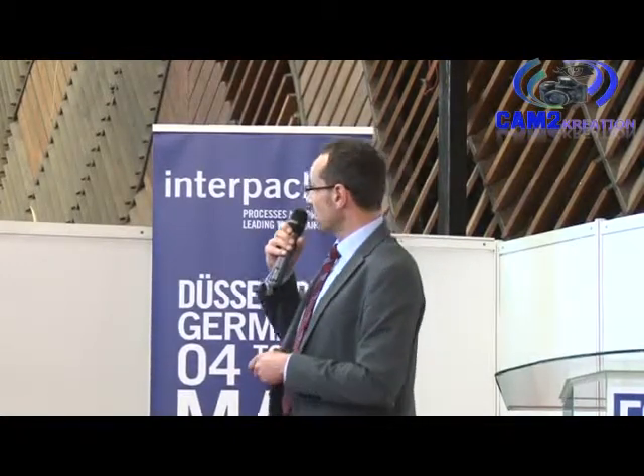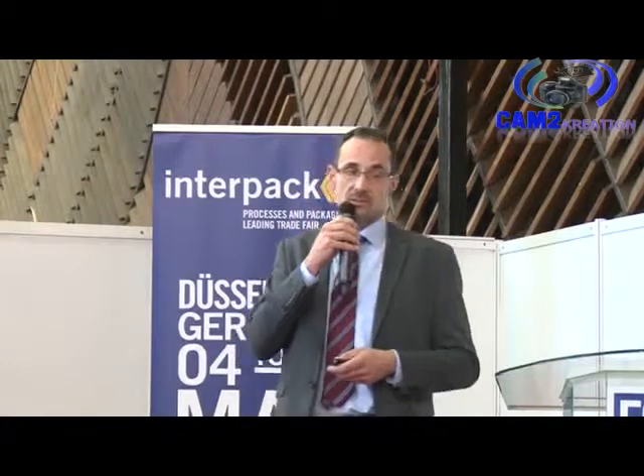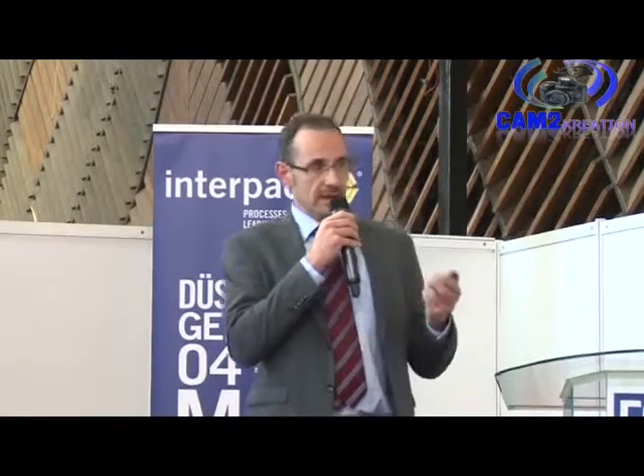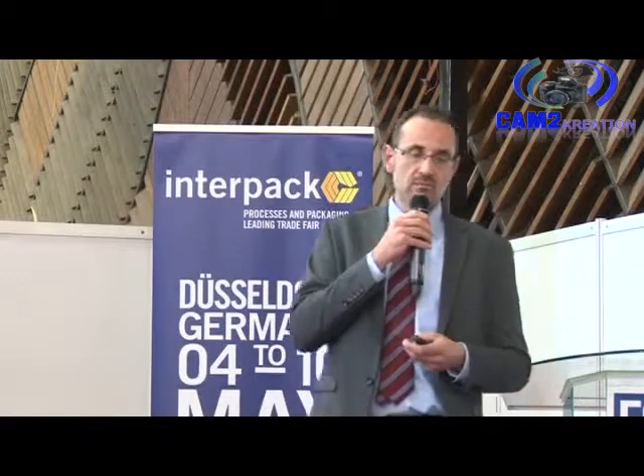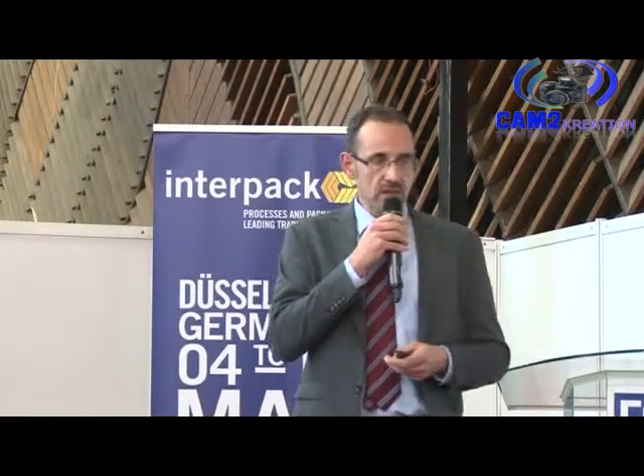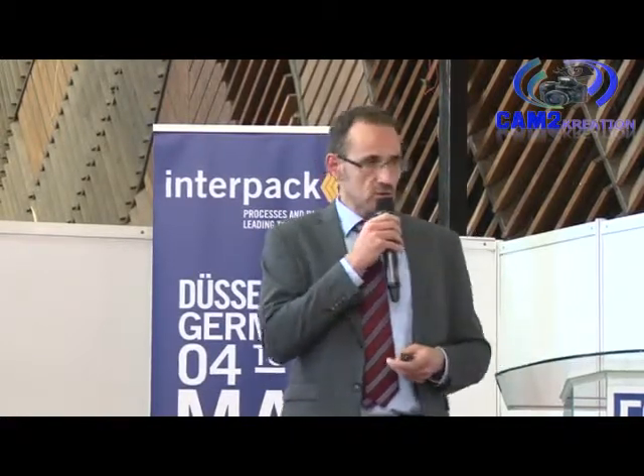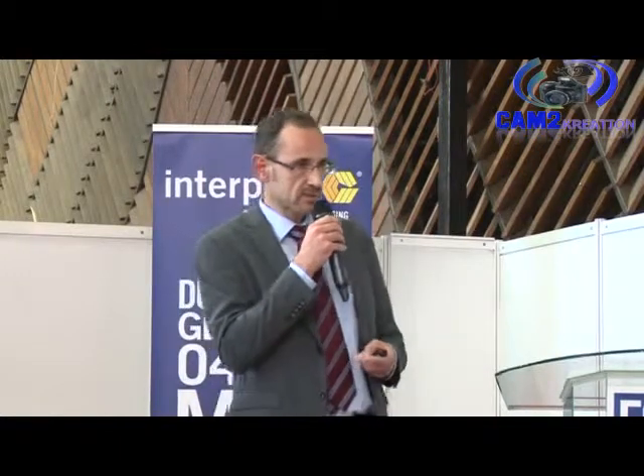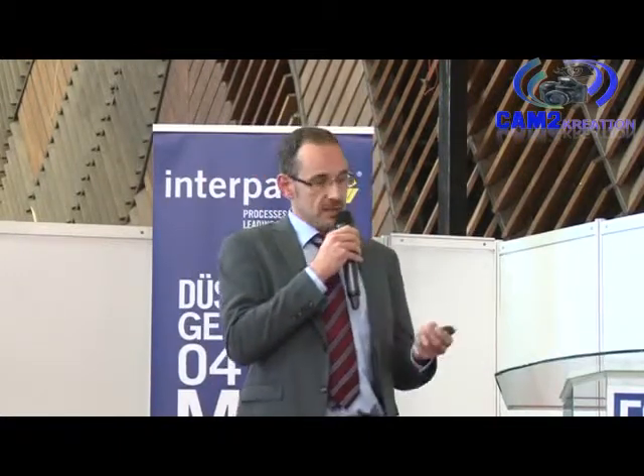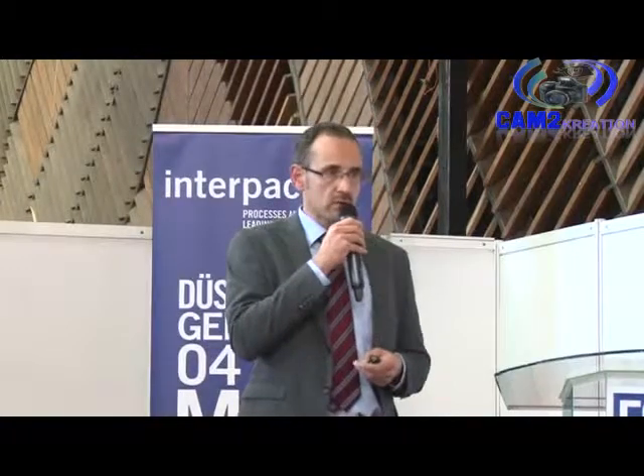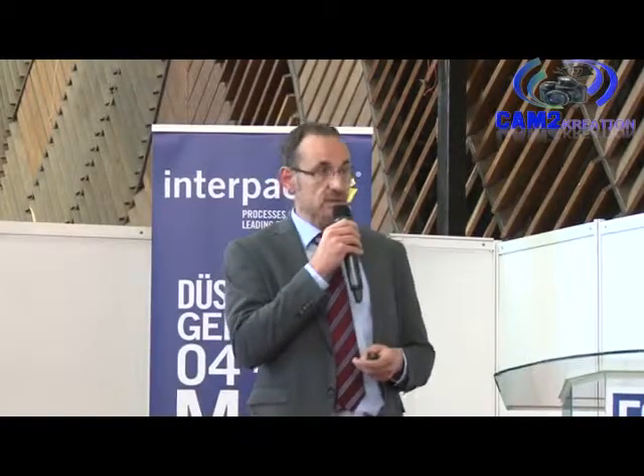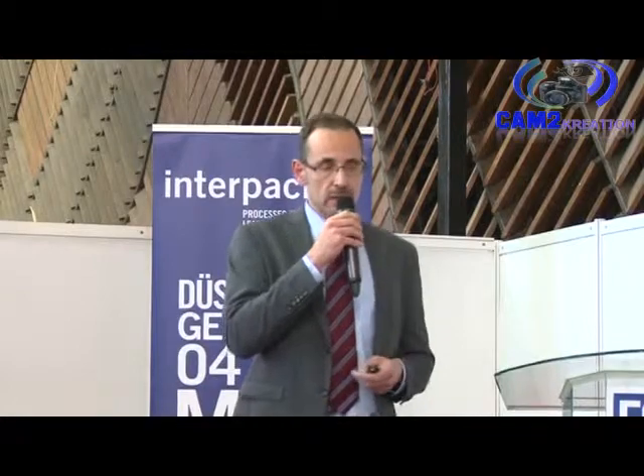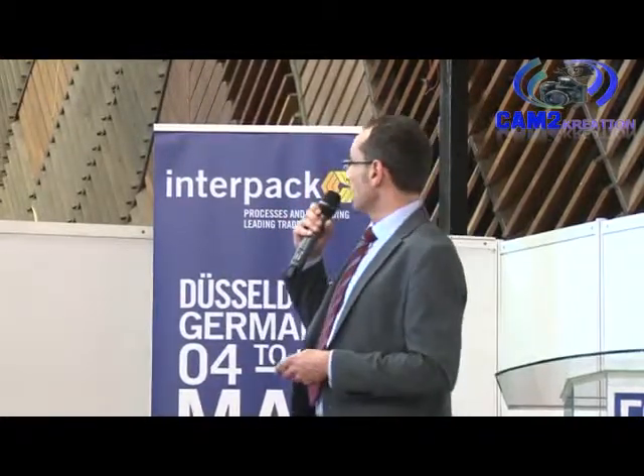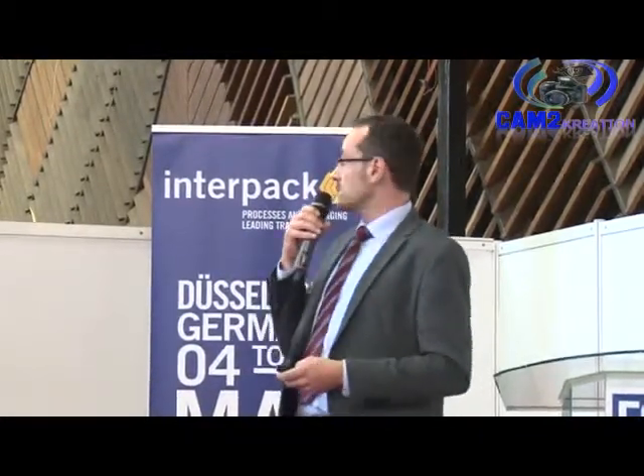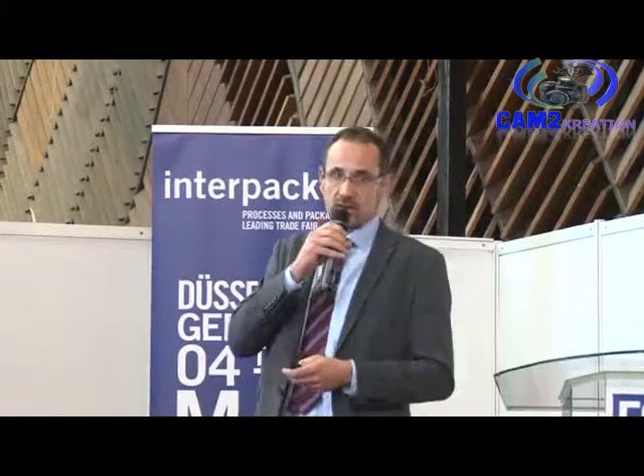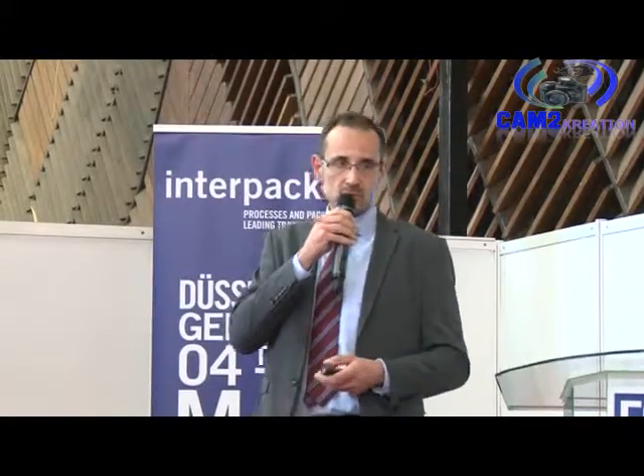And the last point is the gas barrier. As already said, nylon doesn't give you the high gas barrier of EVOH, but it gives you what we call a medium gas barrier, which is fundamentally already suitable for smoked products, smoked meat products like bacon and ham. It's used for smoked fish. You can pack it just with nylon. You can increase shelf life heavily, and this leads to a prolongation in shelf life. It will keep the quality of your foodstuff stable.